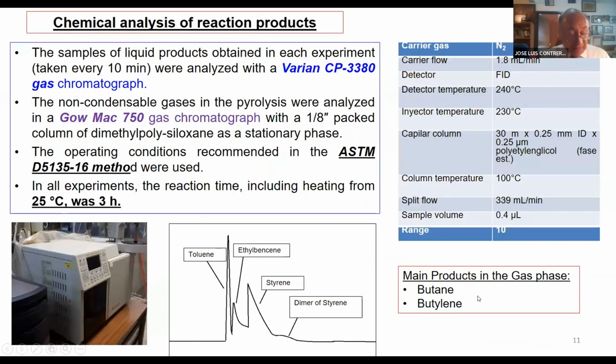The analysis procedure for the samples in liquid and gas phase was chromatography. Shown here are the columns, chromatographs, and operating conditions of the Varian chromatograph. Chromatograph of the main products in the liquid phase is also shown, which were toluene, ethyl benzene, and styrene. The recommendations of the ASTM method were followed for this purpose.